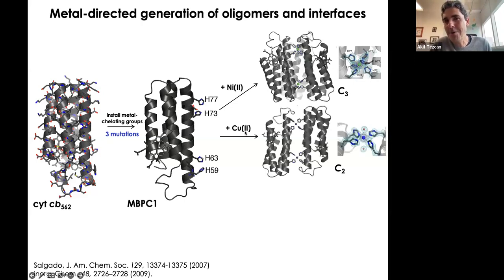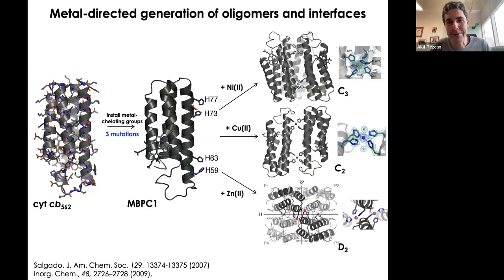Copper(II) is next to nickel in the periodic table, but it prefers a square planar geometry. So what we saw was that copper(II) imposes C2 symmetry to form a dimer that has 2 pairs of histidines in a square planar geometry. And one to the right in the periodic table, that's zinc(II). Now zinc(II) has a d10 electronic configuration. It likes a tetrahedral geometry. And what we found was that it imposes the formation of a tetramer that has D2 symmetry, because all of the zincs like to find a tetrahedral coordination of amino acids.